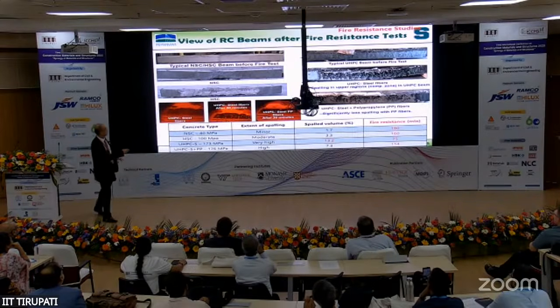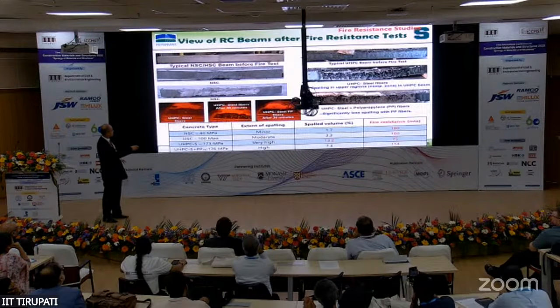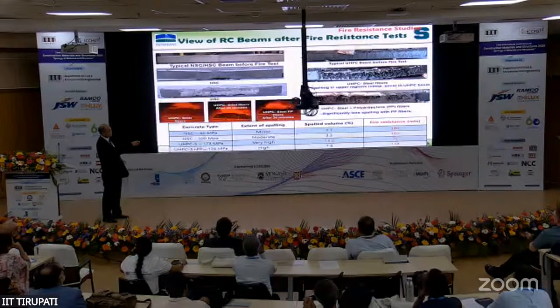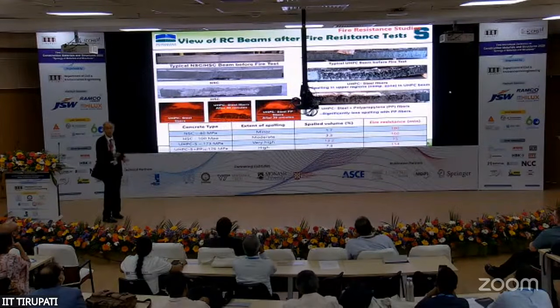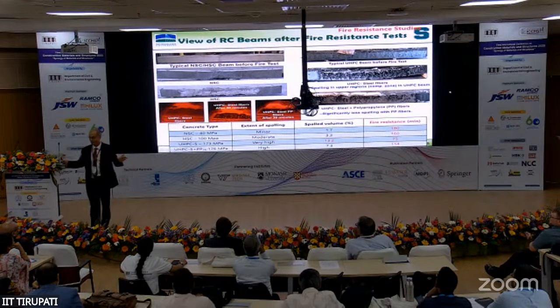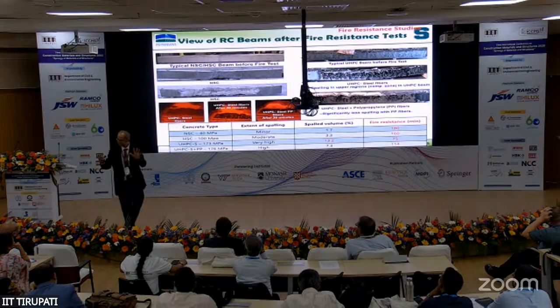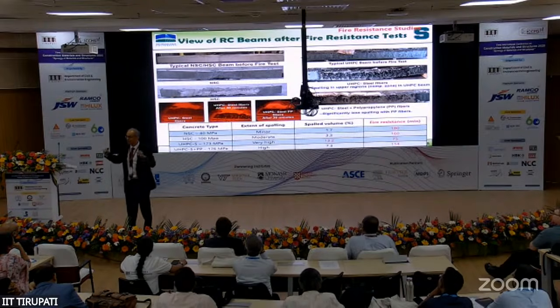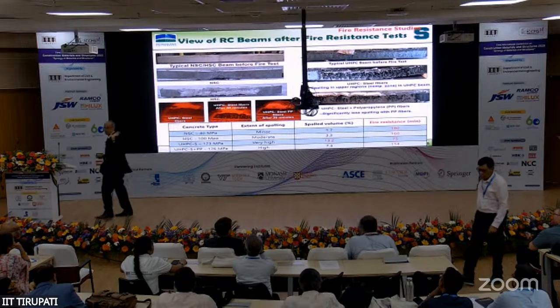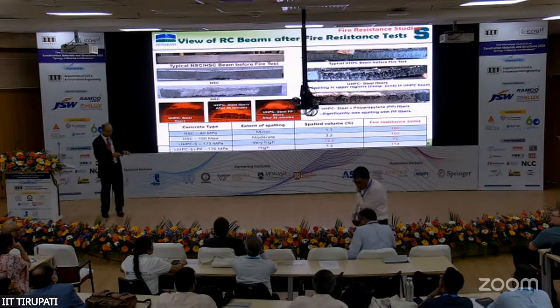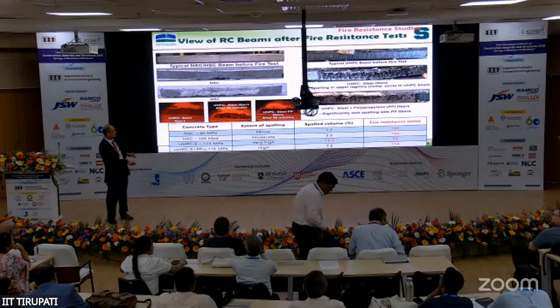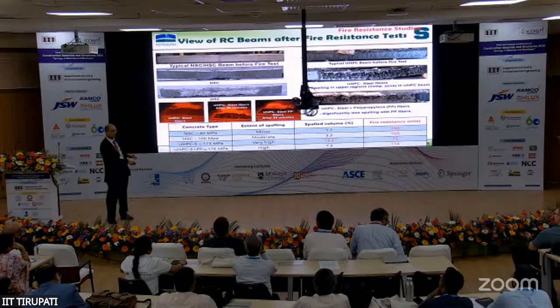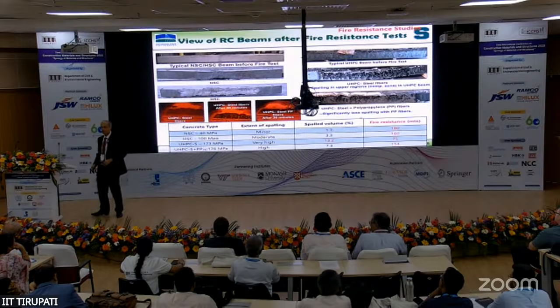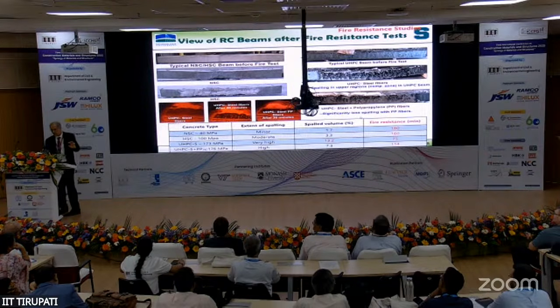This is normal strength concrete beam, high strength concrete beam, UHPC beam with steel fibers alone. If you add polypropylene fibers, they melt early at 160 degrees, create channels. Basically, it increases the permeability. Think of it that way. And the pore pressure gets alleviated. So you have lesser spalling, much lesser spalling. And they fail, as you see, normal strength concrete beam, it fails in 180 minutes. High strength concrete beam, UHPC, and look at the percentage of volumetric spalling. When you add fibers, you can reduce it, but not fully.